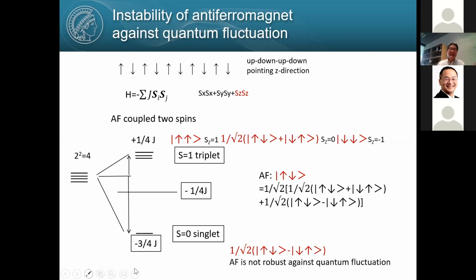This is elementary quantum mechanics. The spin singlet state gains energy of -3/4 J, and the triplet state gains 1/4 J. That's something you can find in a textbook. And the anti-ferro state, like the up-down situation, is a superposition of the triplet configuration and the singlet, right? So the energy for anti-ferro, only up-down with no quantum fluctuation, is -1/4 J, the average of those two energies.